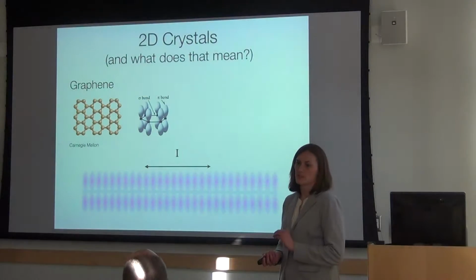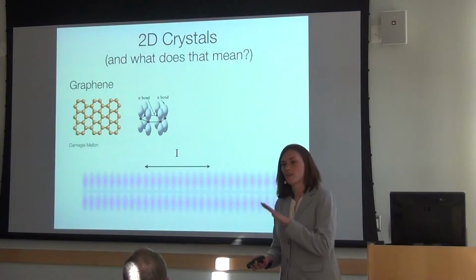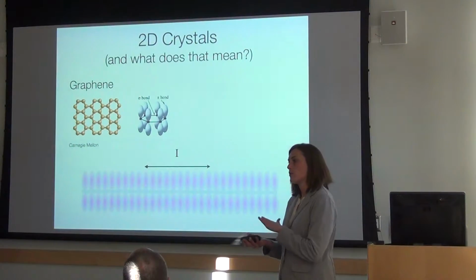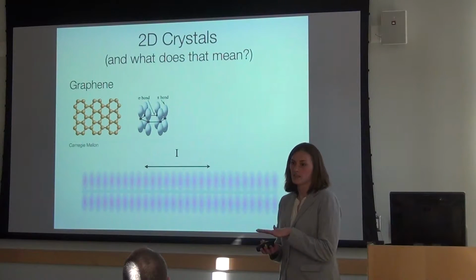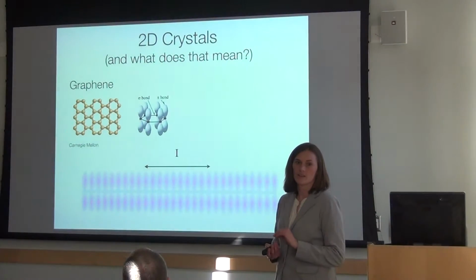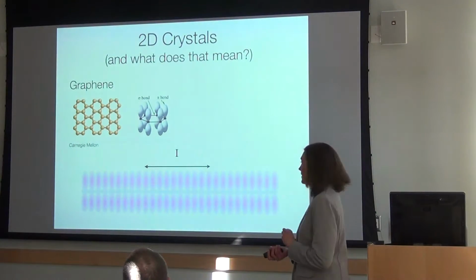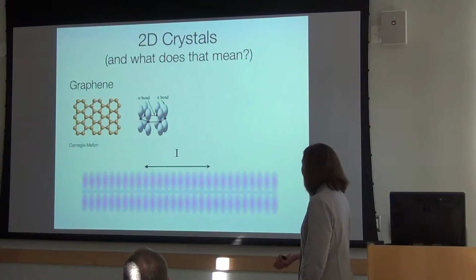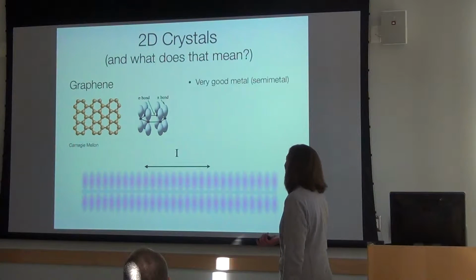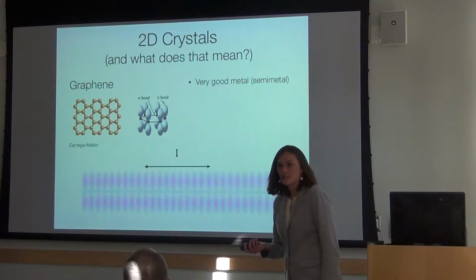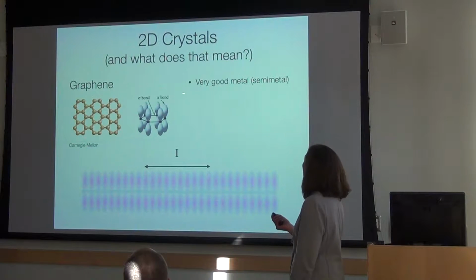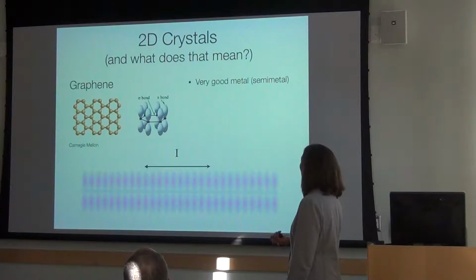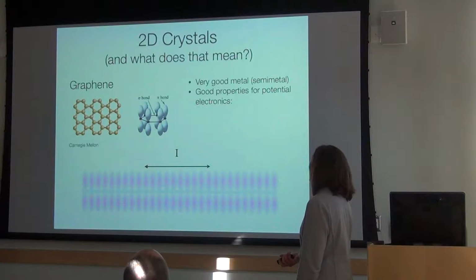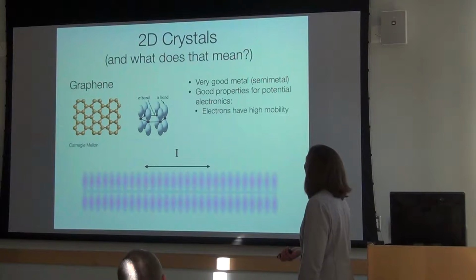And it actually changes when you go from a bulk material into a single layer. You've broken a real symmetry in the lattice. So you've changed the electronic properties fundamentally by taking it to this two-dimensional limit. And graphene is a pretty remarkable material. Even in a two-dimensional sheet, it's a very good metal. It's actually a semi-metal. And it has good properties for potential electronics.